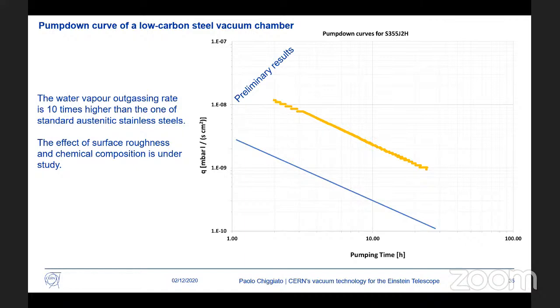And when you pump down without any bakeout, in effect, the water vapor outgassing rate is 10 times higher than the one used as a standard for austenitic stainless steel. This difference is probably due to the surface roughness or the chemical composition, and this is the subject on which we are focusing our attention these days. This is done by different techniques, in particular surface analysis, to understand what is going on there.